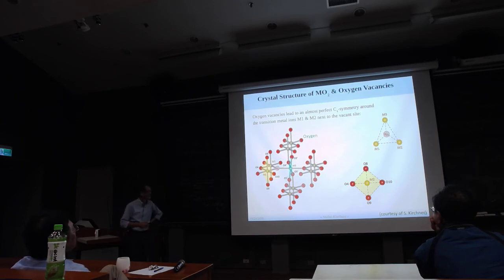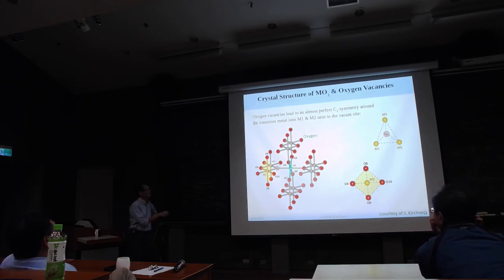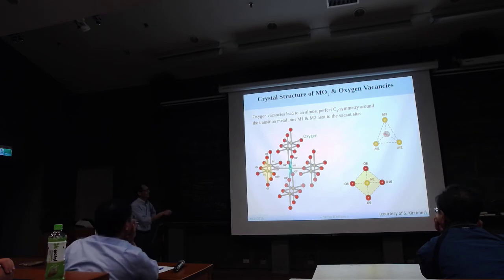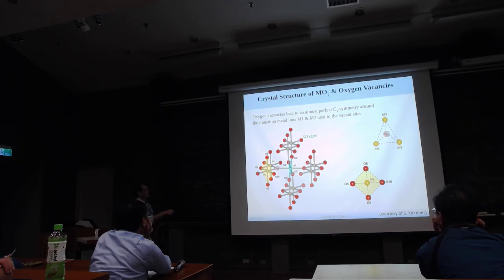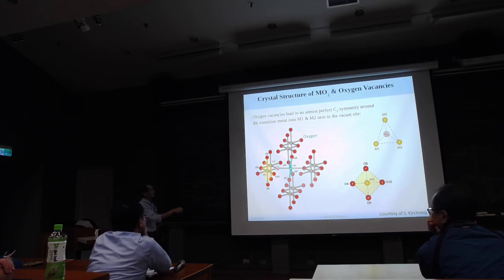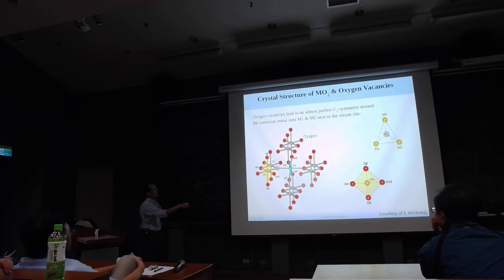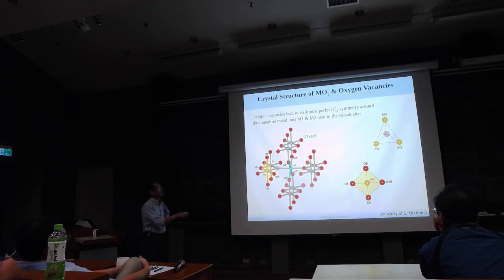So this looks a little bit complicated, but this is the microscopic physics for this. This is the crystal structure of ruthenium dioxide and iridium dioxide. They have effectively the same crystal structures. Here's oxygen, and this is metal, iridium. So this forms this isosceles triangle. For example, assume one oxygen atom is missing. So this is missing, and surrounding it are three iridium atoms. And this distance is slightly longer than this distance.